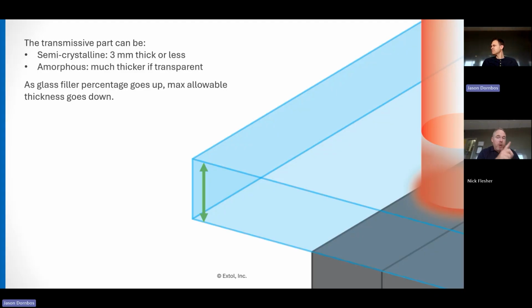I should throw out the caveat of fillers. If you've got talc, some crummy regrind, or high glass content, you're probably not going to get 95% of the material's wall strength. But I will say I've seen 30% glass filled PA6 where it's breaking everywhere but the weld. So one might call that 100%. I would call that your design doing what it's supposed to do, which is you've put the stress elsewhere instead of in the weld.